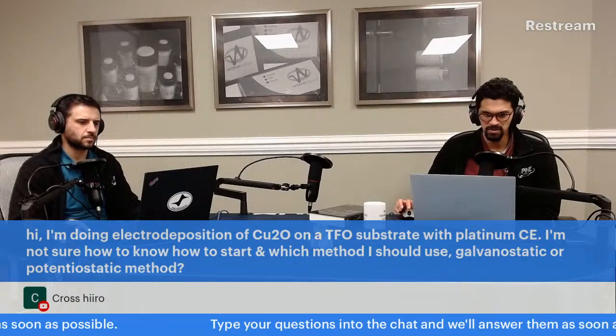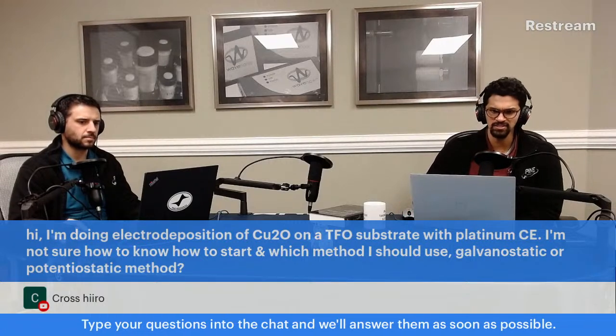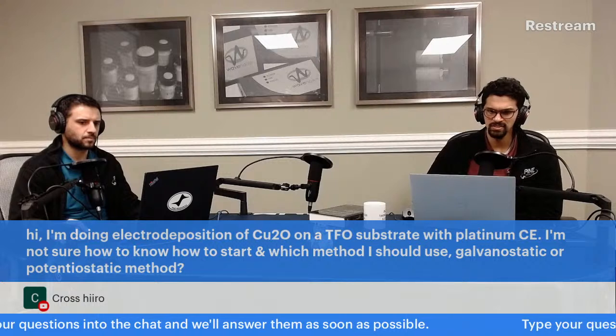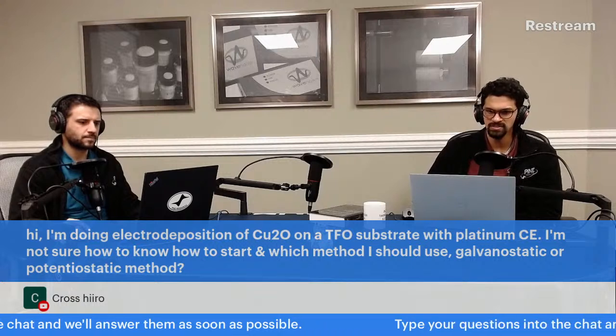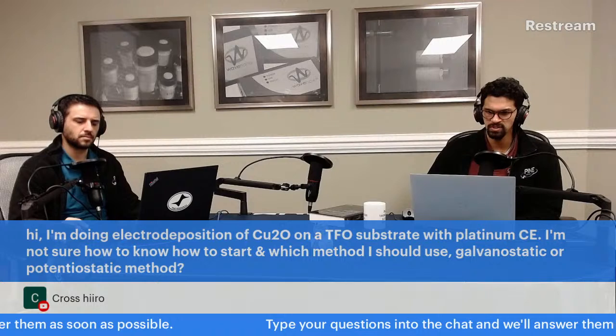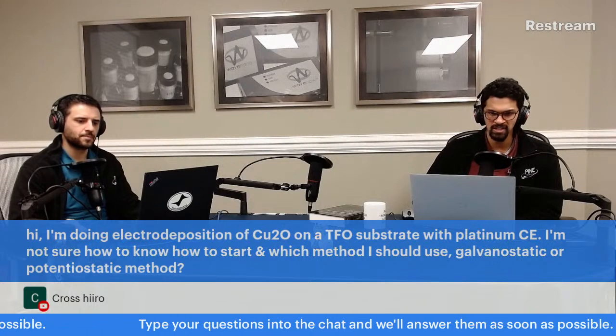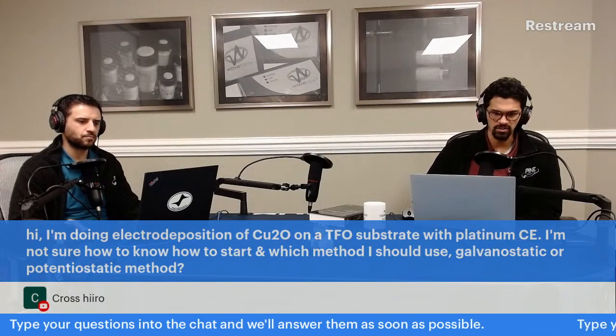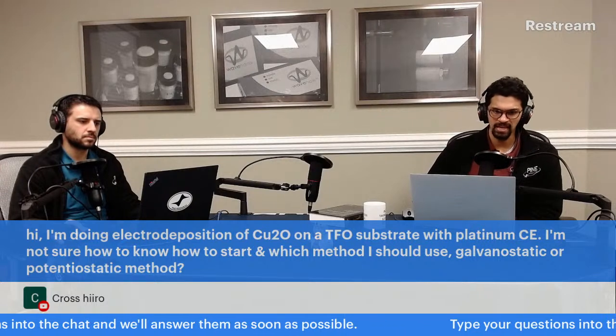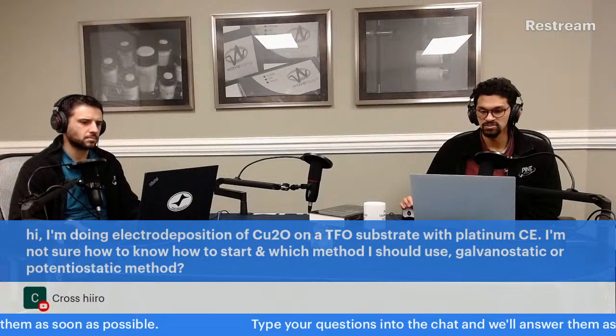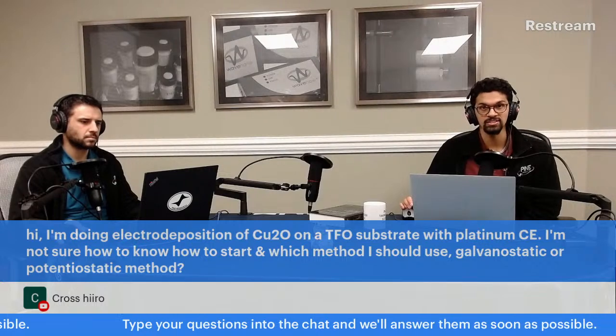Cross Hero says, "Hi, I'm doing electrodeposition of what looks like copper oxide on FTO substrate with a platinum counter electrode. I'm not sure how to start, with which method. Should I use galvanostatic or potentiostatic method?" And Cross is using a silver chloride reference electrode. My recommendation, if you were starting out, is to do a potentiostatic experiment.